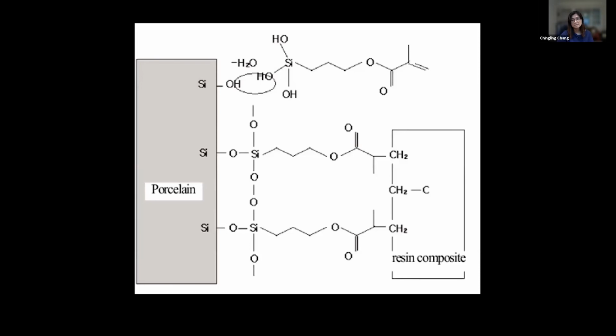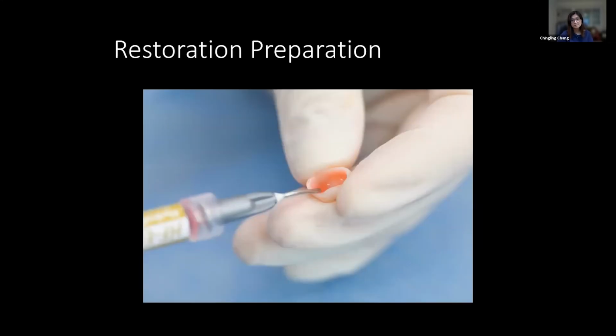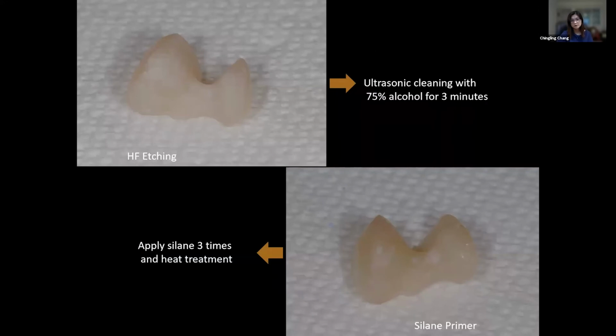And so the silane is very important to create stronger bonding between porcelain and the resin. So this is how you etch the porcelain surface. And after you etch the porcelain surface, you can see the surface become rough, like a foggy looking surface. And then you use 75% alcohol to soak this restoration for 3 minutes to remove the fragile remaining particles on the porcelain surface. And then you apply silane on the porcelain surface.